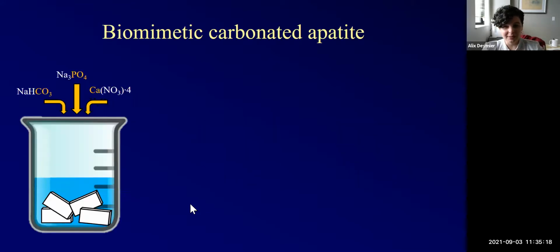So isolating mineral from the bone is very difficult. You cannot get rid of that collagen without really affecting the composition of bone mineral. So what we do instead is we make our own biomimetic carbonated apatite. You just take a carbonate containing moiety, a phosphate containing moiety, and a calcium containing moiety, and you mix them in an aqueous environment at temperatures close to body temperature. If you do that,